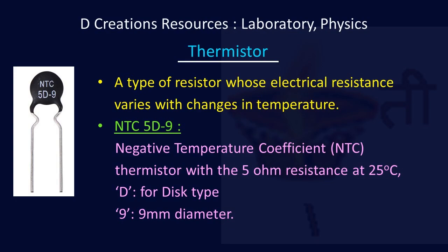In order to make a thermistor, two or more semiconductor powders made of metallic oxides are mixed with a binder to form a slurry, and small drops of this slurry are formed over the lead wires. Now they are put into a sintering furnace for drying. Once these metallic oxides dry up on the lead wires, they are sealed by putting a glass coating on it. The glass coating will also make it a waterproof device and hence improve its stability.